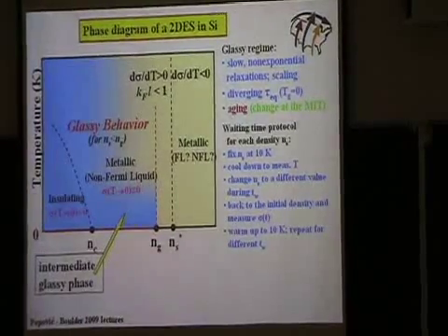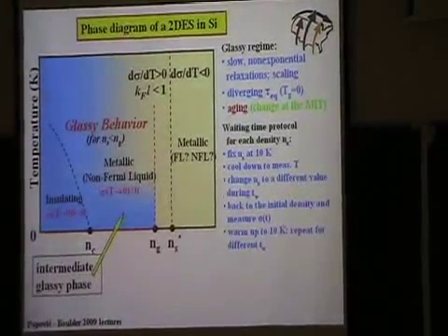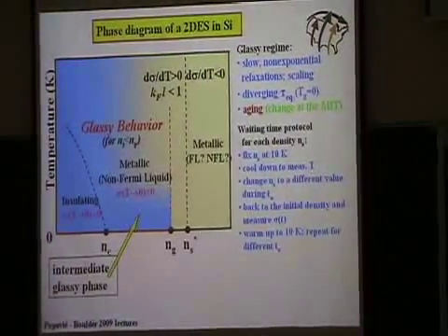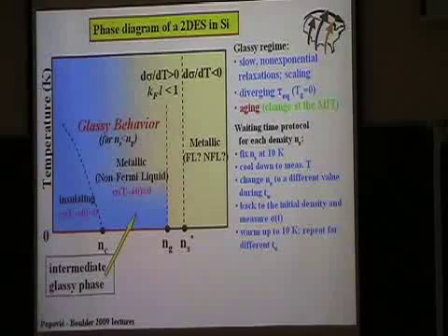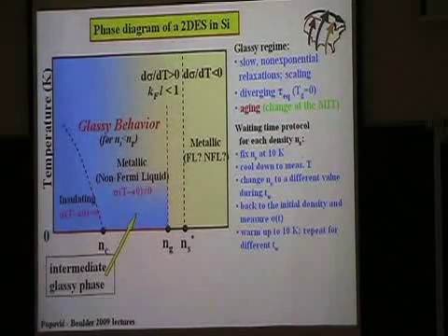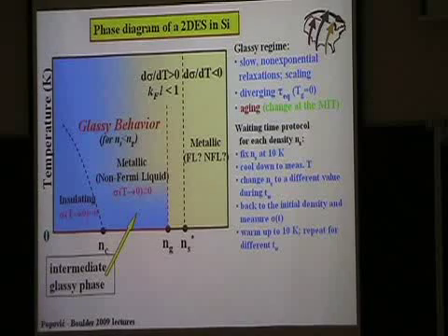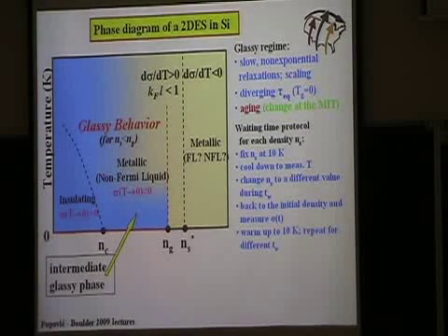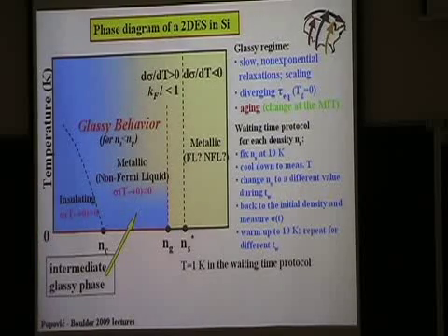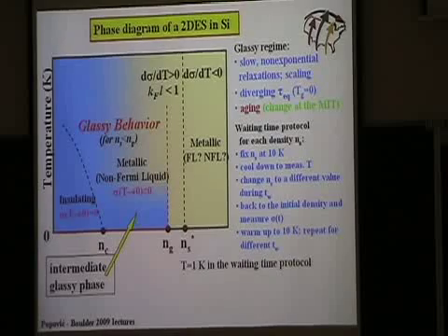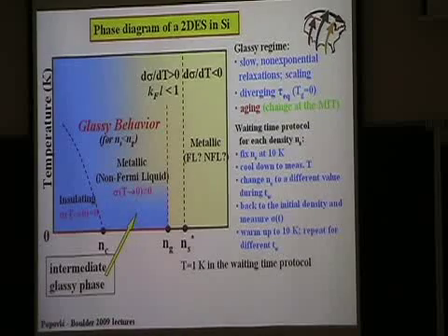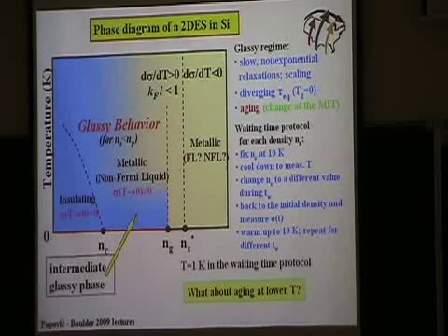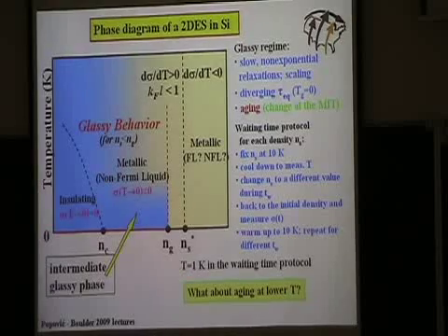Here is just a description of what I had yesterday of this waiting time protocol, which is the protocol that Michel called intermediate, where we change the density to some value during the waiting time, and then we go back to the original initial value and look at the relaxations. So those aging studies were done at temperature 1 Kelvin because I showed you that the equilibration time is astronomical at that temperature, so the system is always out of equilibrium. Of course, you can ask also a question, what happens at lower temperatures as we approach this ideal glass transition?